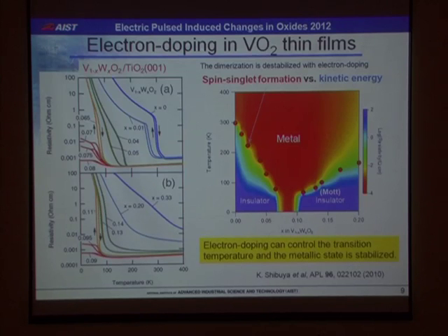Let me start from chemical substitution. It is possible to stabilize the metallic state by chemical substitution. The substitution of tungsten for vanadium is known to reduce the transition temperature most effectively. The valence state of tungsten is 6+, such that that of vanadium changes from 4+ to 3+. This means electron doping into VO2. We fabricated this V1-xWxO2 epitaxial thin film on a titanium dioxide (001) substrate by pulsed laser deposition.